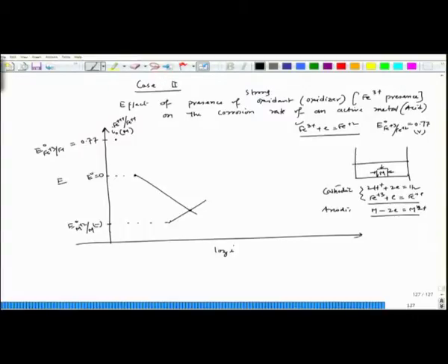So, now you could see that this entire corrosion process is divided into one anodic reaction and two cathodic reactions, and both these cathodic reactions are taking place on the metal surface. That is why we are considering I0 for Fe3+ to Fe2+ on the metal surface. So, it would have its own activation polarization, cathodic as well as anodic.